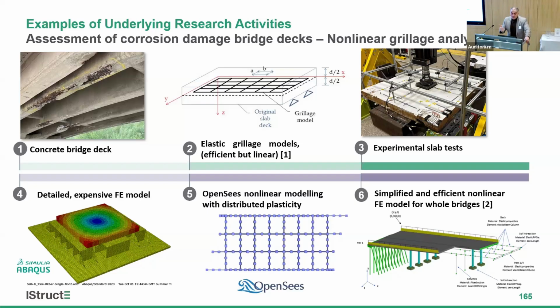In Network Rail, for example, for the level 2 assessment, for metallic bridges, they do a lot of nonlinear analysis. But for concrete bridges, we cannot do it because of the complexity of the 3D modeling of the concrete. But with the fiber model that I've shown you for the earthquake, which is quite common, we can use it. We can essentially develop a nonlinear grillage model that can capture the distribution of the plasticity within the bridge slab.